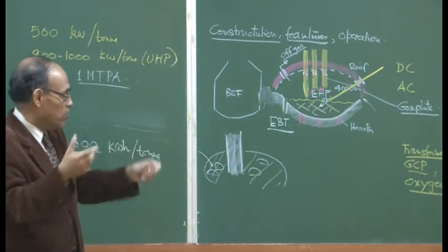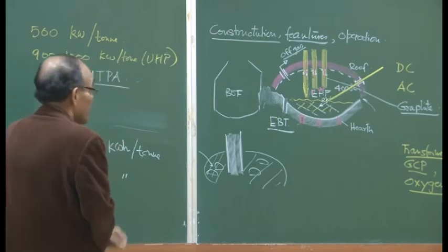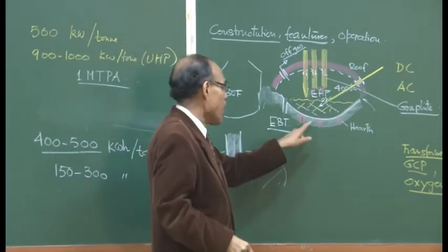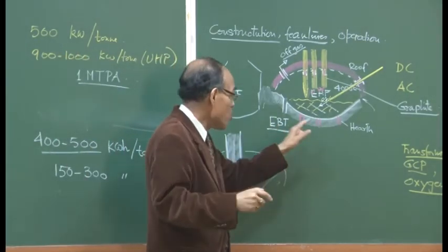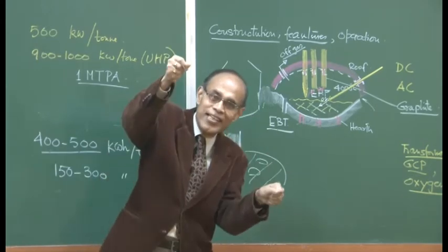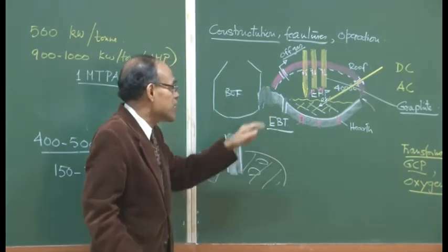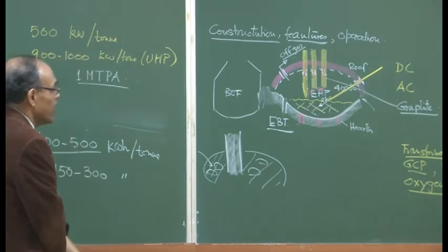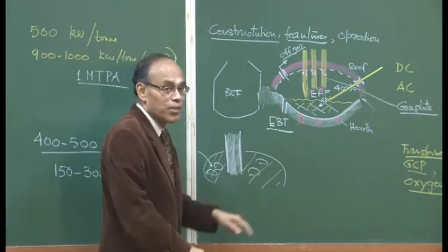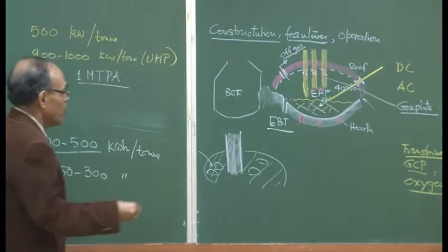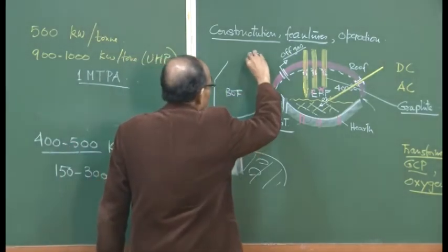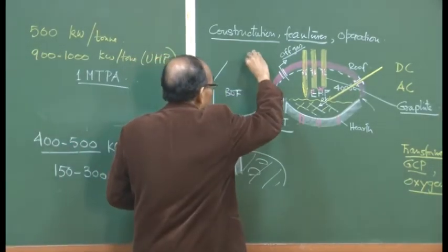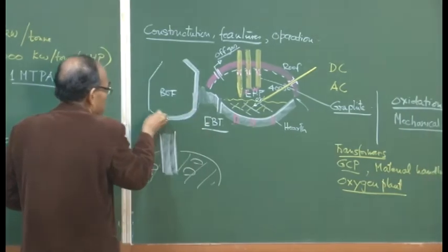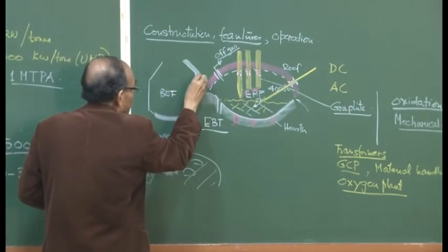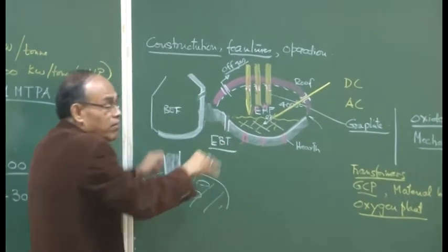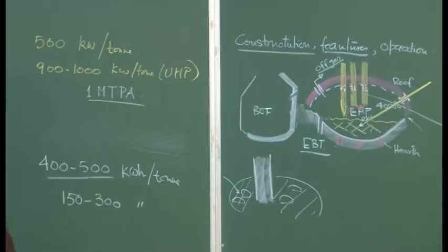So, during the process itself, when they are dismantling, that is a different issue, but during the process they are going to be only marginally tilted, okay, in order to facilitate charging of hot metal as well as draining of molten material itself. But BOF, because they have a tap hole located here, as I have indicated, okay, this is the tap hole in BOF, so it needs to be tilted quite a bit.